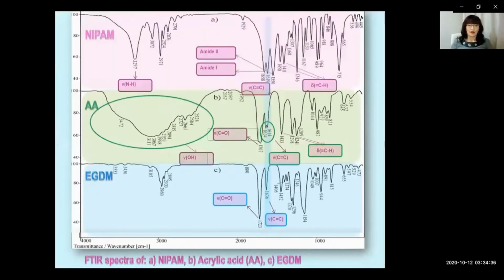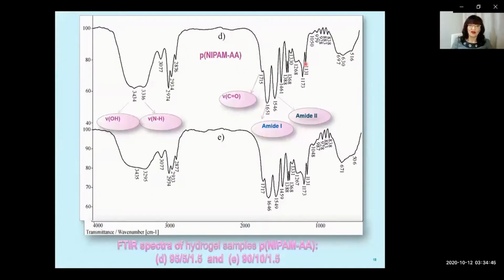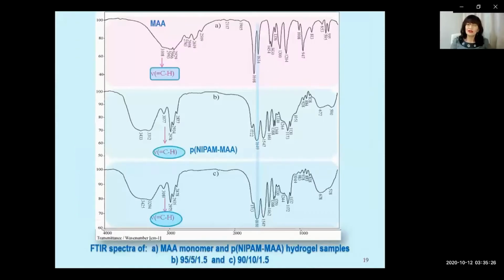FTIR spectra of hydrogel samples, poly-N-isopropyl acrylamide co-acrylic acid with 5 and 10 molar % of acrylic acid have structures different from reactants. The presence of new bands, which are absent in the spectra of monomers and cross-linker, and absence of absorption band from 1620 to 1640 reciprocal centimeter, which originate from the carbon-carbon double bond, confirm successful polymerization. This bond is broken down in copolymerization reactions.